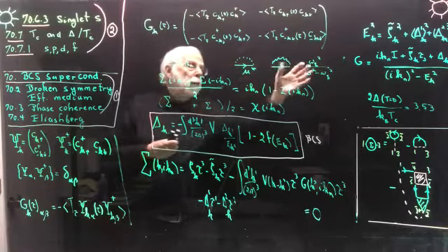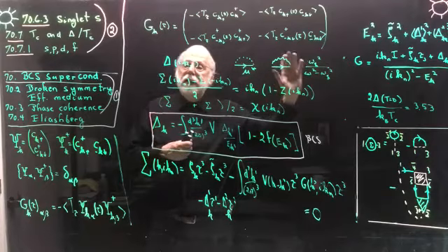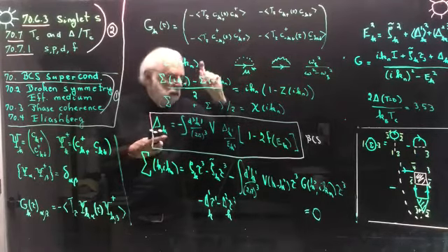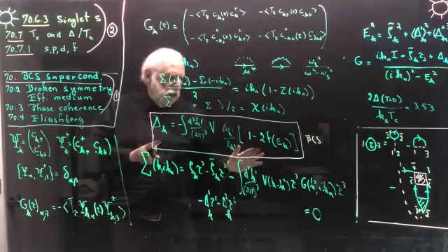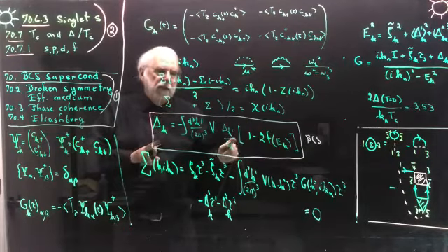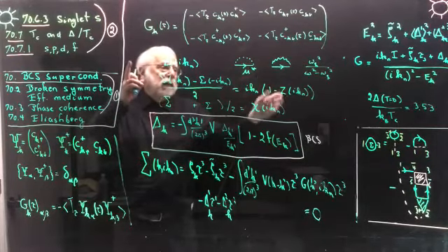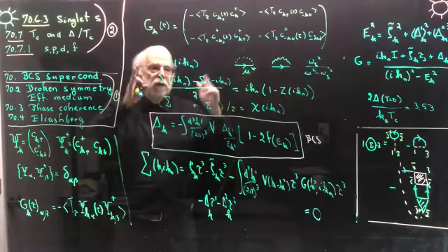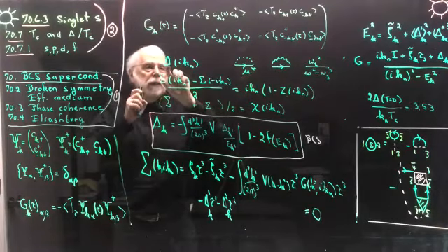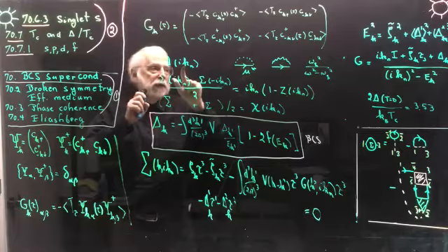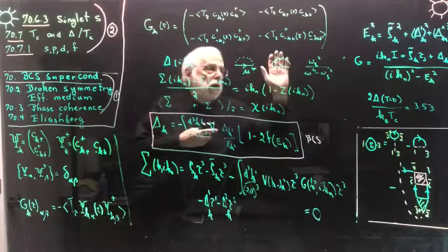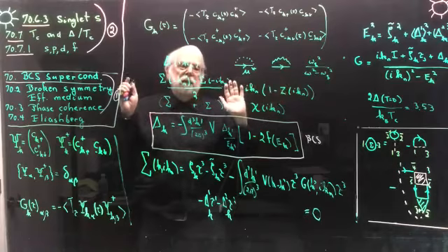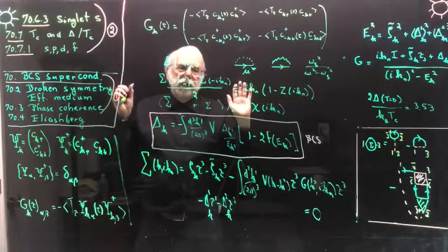You can see that the peaks in the phonon density of states show up in this. More than that, because the BCS equation that you see here is nonlinear, there are harmonics of these phonons. So it's very beautiful. From tunneling, you can measure this delta as a function of frequency, and you see the peaks in the phonon density of states, and you see the higher order harmonics. So it's hard to make a better theory.